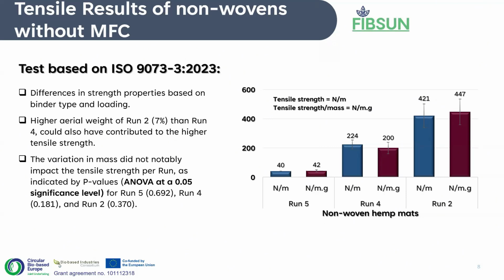However, in the case of PP, we see that increasing the loading, which is normally the case, increases the tensile properties of the nonwoven. So about a 2 times increase in tensile properties with a 3 times increase in loading. And